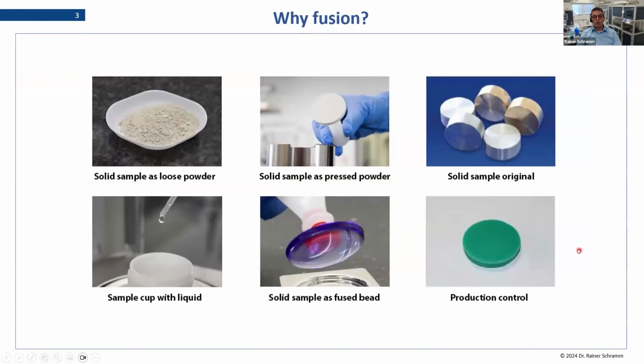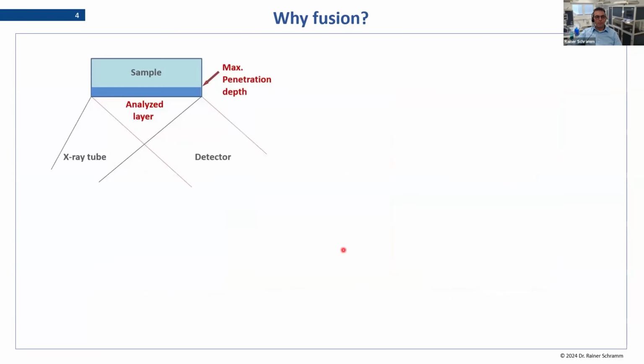If we look at the sample preparation techniques we normally use for XRF, we can use a sample cup where we can put liquids in or loose powders, or we could use pressing technology to make a press pellet out of a powder, or we can dissolve the powder directly into glass to get a fuse bead. And of course, there are other techniques, like measuring metal or plastic samples directly. But let's talk today about fusion and why we need to do that.